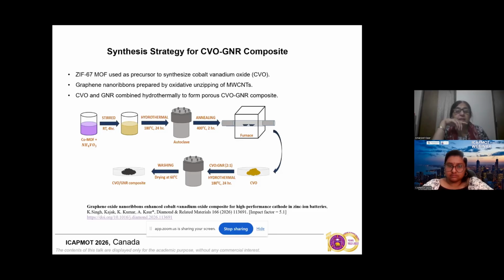So in this we have a vanadium oxide cage in which cobalt is entrapped, and then we have graphene nanoribbons. They are prepared by the oxidative unzipping of multi-walled carbon nanotubes, and then we have combined CVO and GNR hydrothermally to form the porous CVO GNR composite. So they are stirred, then we have the hydrothermal autoclave, then annealing at 400 degrees Celsius, and then we wash it multiple times to get the CVO GNR composite.